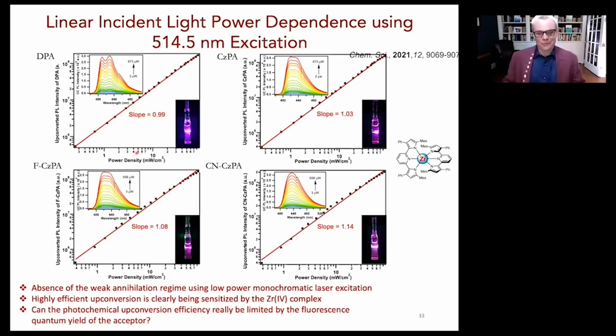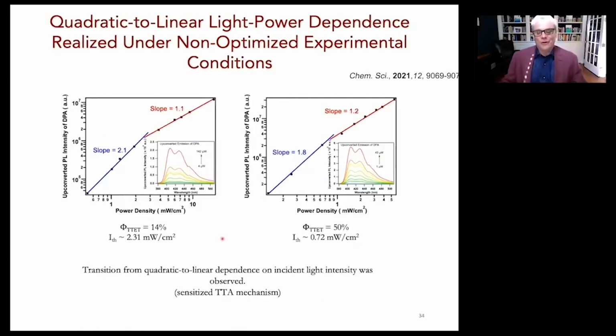So you kind of start wondering, we have this absence of the weak annihilation regime. And then we think about, obviously, this means very high efficiency upconversion being sensitized by this complex, unprecedented to us. And then it was like, can the photochemical upconversion efficiency really be limited by the quantum yield of the acceptor? That's almost what we were thinking we were seeing. So then, of course, we just took a step back and said, well, let's just make sure we can see quadratic to linear.